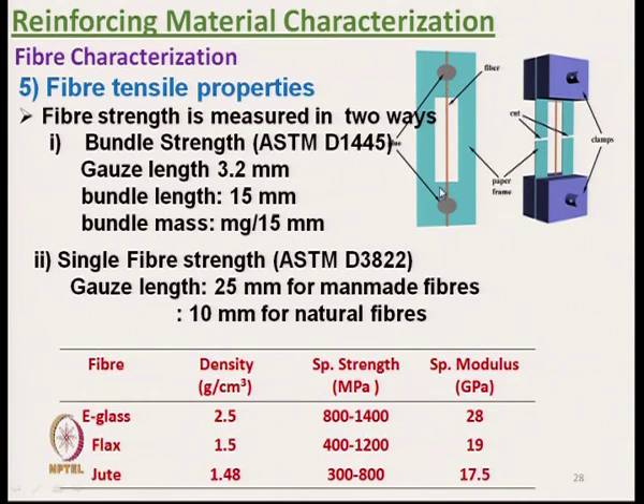Okay, this is the fiber, and it is fixed on a frame, and these are gripped by the tensile tester, and then this frame is cut at the side, where only fibers are exposed, and then we can get the fiber strength. This is the paper frame, and the paper frame along with the fiber is placed on the tensile tester. After that, these two sides are cut, and these are the clamps, and then we can test the single fiber strength.